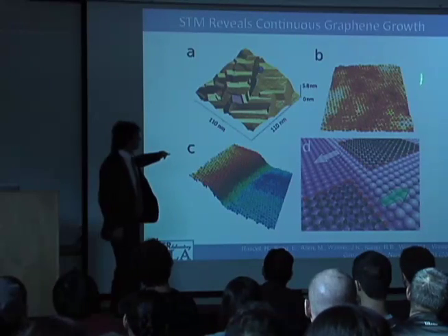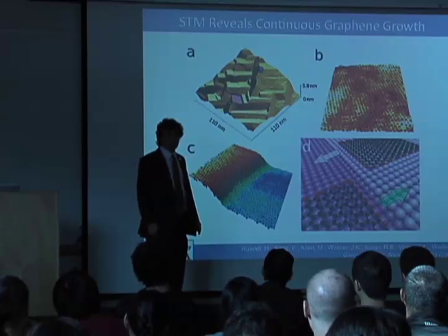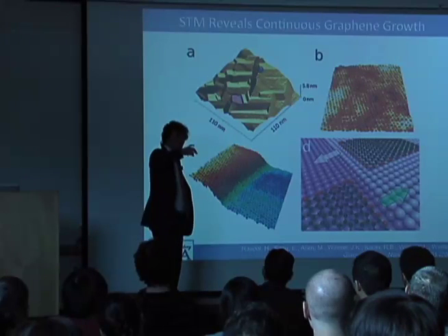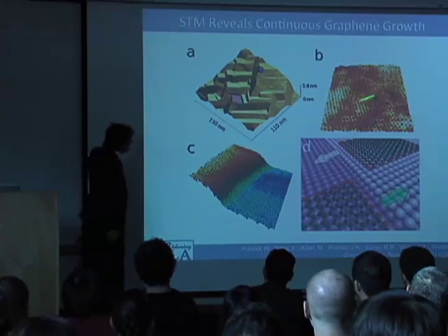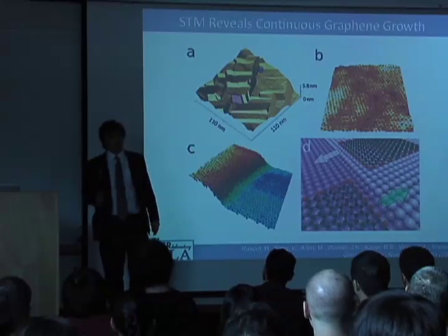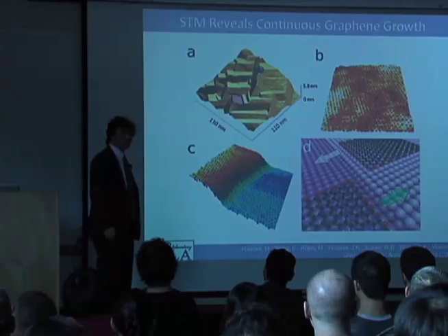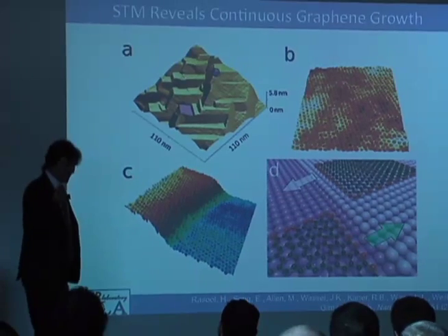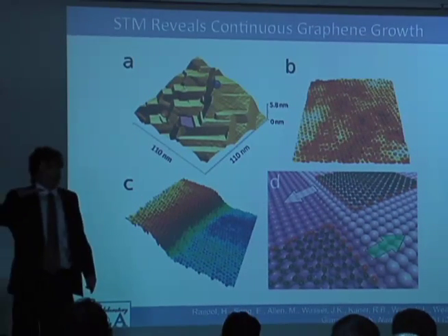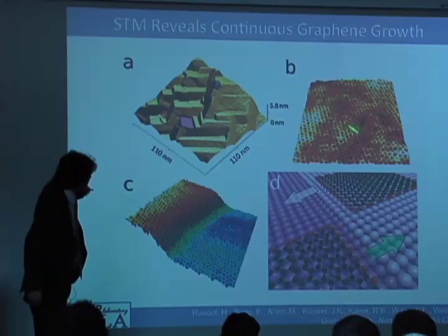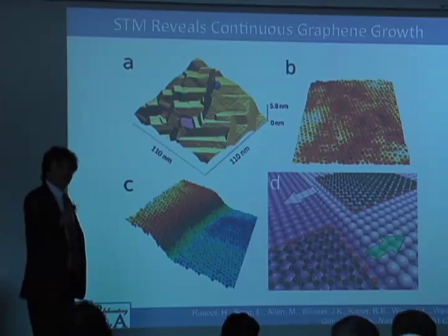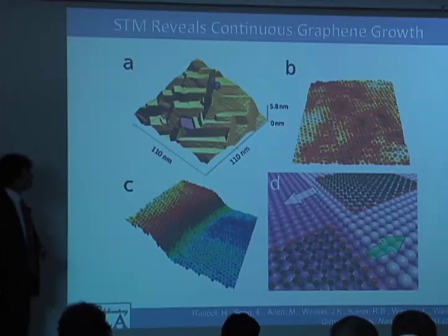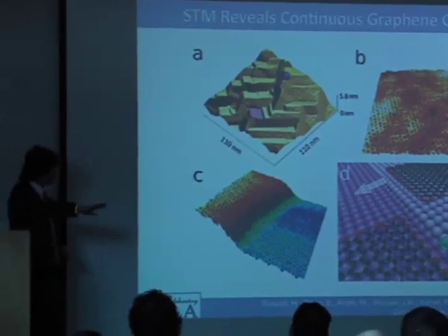And if you look here, this is one of the most beautiful pictures of graphene that you'll ever see, because every 6-membered ring, every carbon's there. If you take graphite, you only see 3 dark carbons and 3 lighter ones because of its structure. But here, all 6 show up. All right, I realize from where you're sitting, you're probably saying, that is not a beautiful picture. In fact, what you're seeing is white and red and yellow and all these different colors. But keep in mind that STM measures an electronic density map. And so what you're looking at is electronic density. Well, the carbon is flat. It's essentially perfect. It's the underlying copper surface that shows up in these electronic colors, if you will. And so it's interesting that the copper is doing funny things, and yet the graphene just grows separate from it.